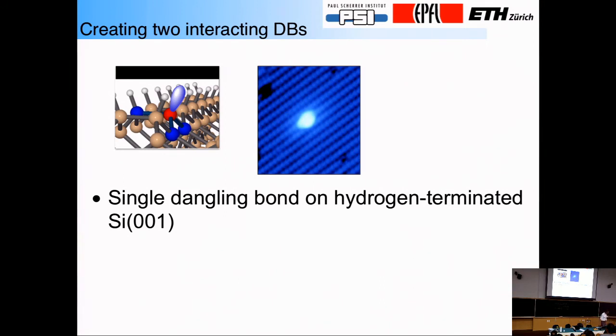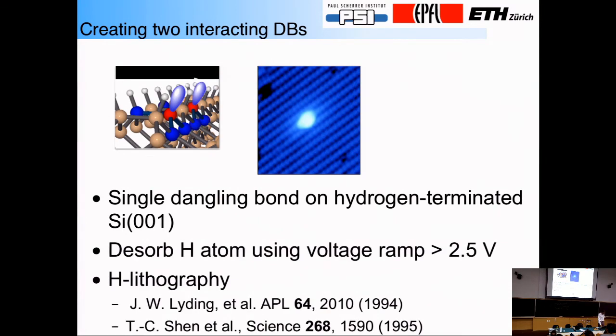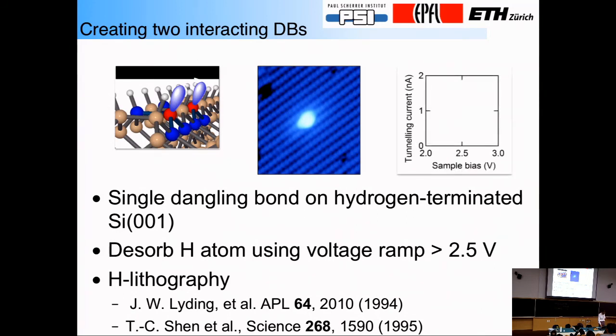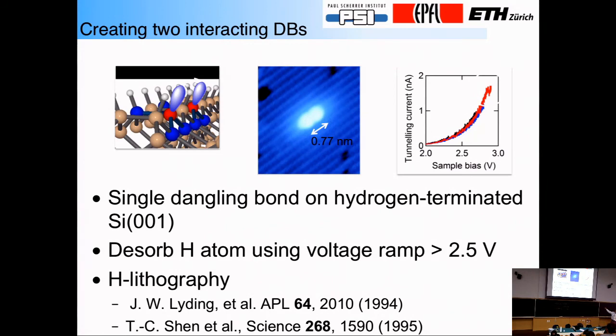Of course, one dangling bond is not terribly exciting. The talk is about many-body physics, so maybe the first thing to do is to look at two. So what we did is we started with one dangling bond, and then we decided to desorb a second one using a voltage ramp next to it, and then look at what the STM images look like. The way we do that is just illustrated in this animation. I just keep hitting this region of the sample with ever larger voltages. And eventually, if I hit with a large enough voltage, I get a bigger object here, which is 0.77 nanometers, almost a nanometer across, where I have two electrons now, which wander around in this little quantum well.